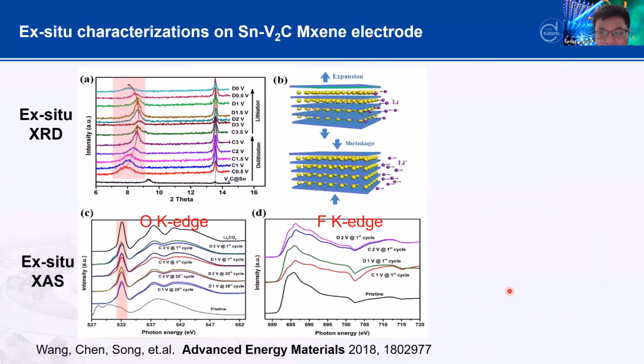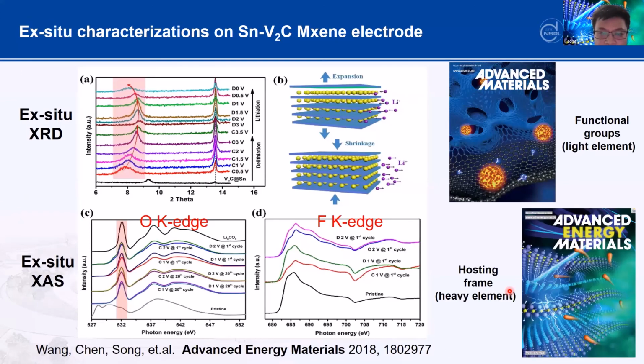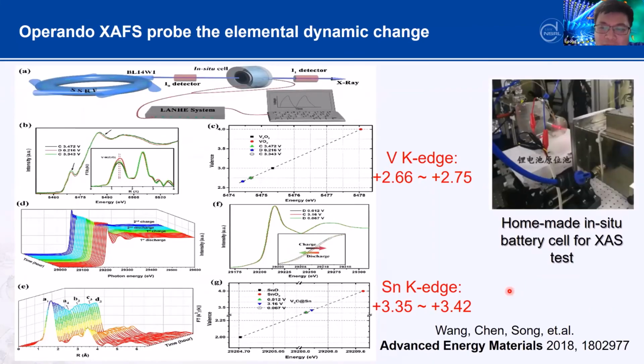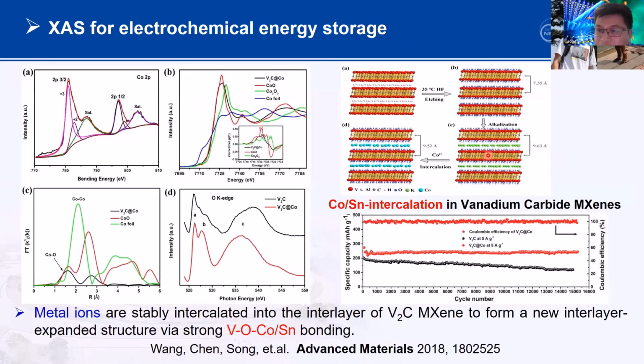Yeah, this is a very good question. During this, we do see some intercalated atoms, the metal, change the valence state. But we cannot really see whether it becomes larger, especially across different layers. In the same layer, they may try to aggregate together, but between different layers, they have the interlayer material here, so that will maybe block these two. So in the same layer, this metal may aggregate a little bit during the reaction, but between different layers, I think it is not so easy. This is what I suggest, but I do not have the evidence. Okay. Thank you.